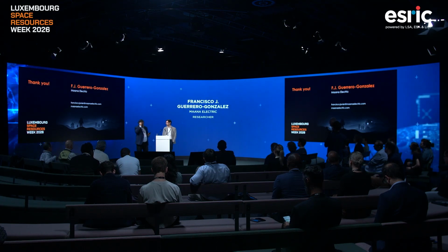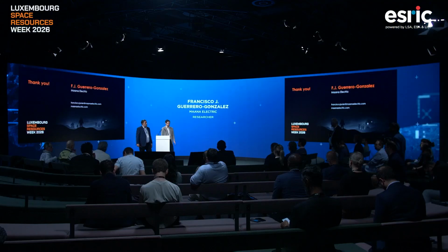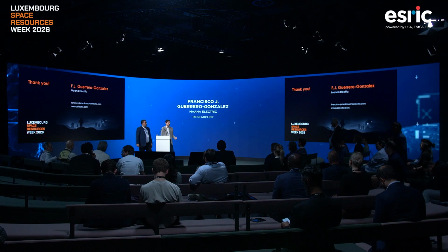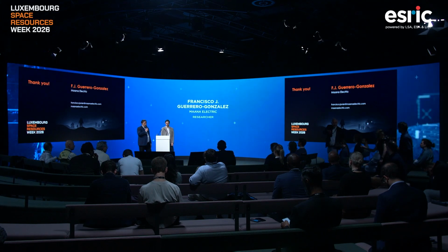Yes, it's actually a real problem. For example, I didn't show results on iridium, but we have seen that most of our iridium is getting consumed just because it's getting chlorinated. And at the end it's chlorinated and dissolved into the electrolyte. So it's a problem. It's one of the challenges of working with chlorides. And it's one of the biggest challenges, particularly for inert anode development or oxygen evolving anode development. Okay, thank you.